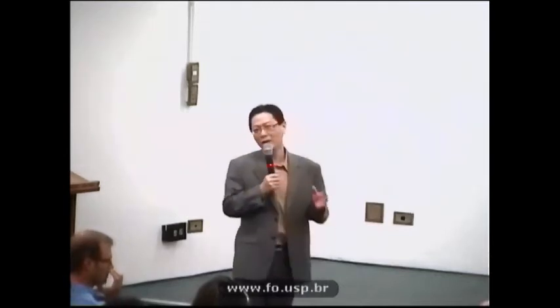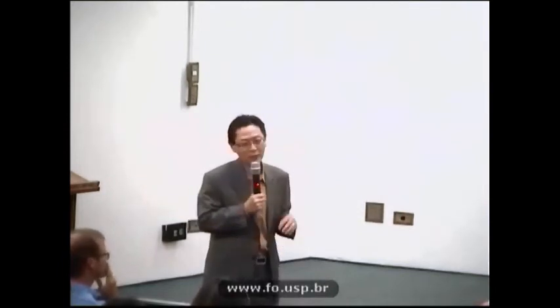So what we did was, when we make those substrates, we soak them in water at 37 degrees for a month. That I didn't mention. And Esteban did those tests too. So that's our lab standard protocol. Those dentins sit in there because Van Thompson is sort of a cement dentin guy, and he said, oh, you've got to let it soak up the water. Otherwise, you cement them on and put them in the water to test, then they suck up water and give you stresses. So that's where we soak them to saturate it.